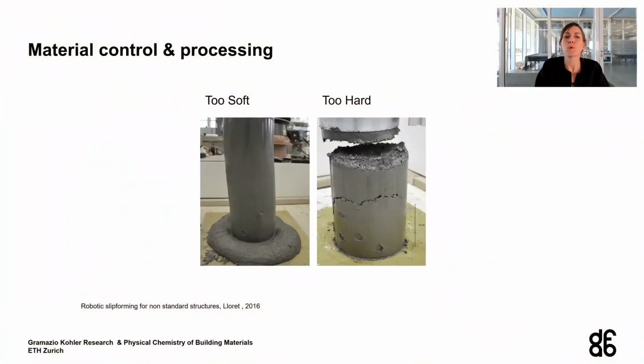So essentially what we do is to assure that the material is not too soft nor too hard. If it would be too soft, it would of course flow out, and when it's too hard, we have too high friction, making the structures break. And in between this short moment of time is smart dynamic casting, or digital casting systems.